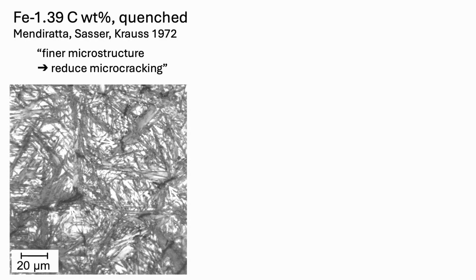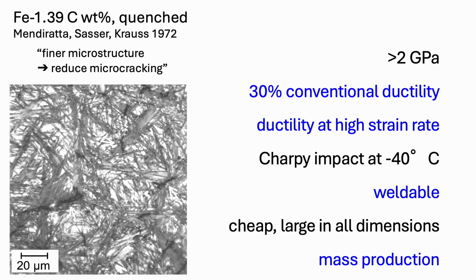Otherwise, you get quench cracking. Okay, the martensite plates will be so brittle that they crack spontaneously, and this is an example. So what I wanted to do was to create a high carbon martensitic steel which does not need tempering, because tempering does reduce the strength. Okay, so I want to use it in the untempered condition and yet have impressive properties of the type that I've listed here.